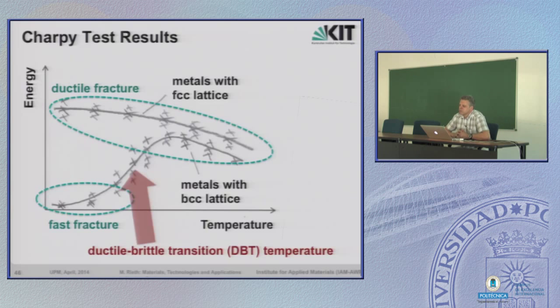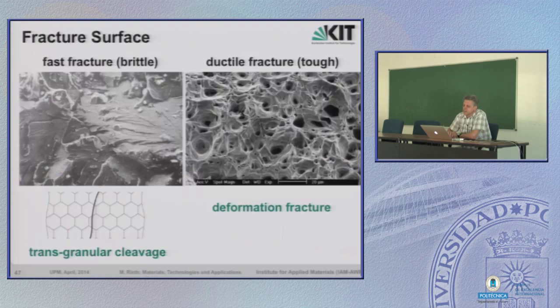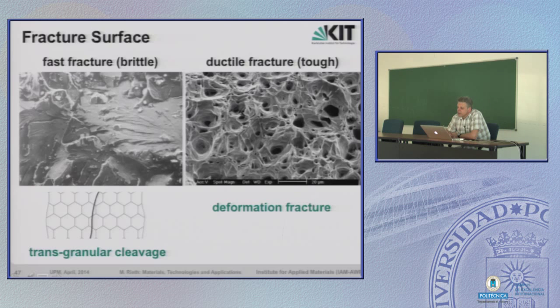In fast fracture we see most often transgranular cleavage fracture — the fracture goes right through all grains, producing large flat areas visible in the scanning electron microscope. In a ductile fracture, you see a very rough surface with many dimples, indicating a large amount of plastic deformation during fracture. Simulation by finite elements shows what experienced designers know: avoid notches. Smooth transitions or large radii are much preferable than sharp notches, because at the tip of sharp notches, there is a local stress concentration.